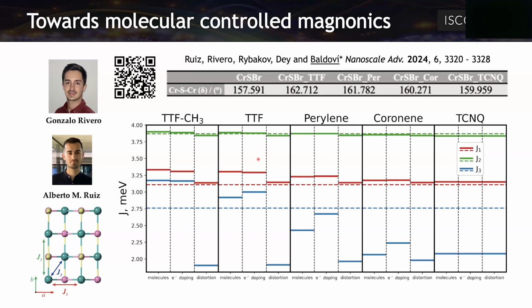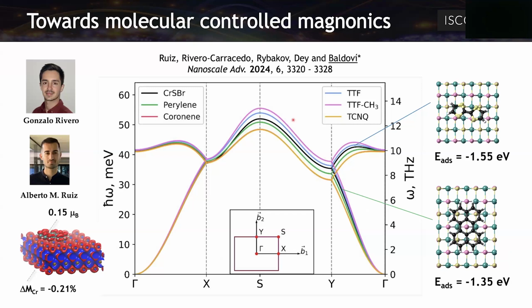This is one real advantage of having now this relation between the energy of the HOMO and the conduction band minimum. And here we have also the effect of the distortion that we observed, so the effect of charge transfer is increasing this from the distortion. Regarding the magnon dispersion, we observed, especially here in gamma Y, because we are affecting mostly J3, as I said before, that the TTF-CH3 is increasing the group velocity, and also the TTF. The black is the pristine, and the other ones, because of the effect of the distortion, are decreasing the group velocity. So it's a way of tuning the magnon frequencies by using molecules, by charge transfer, especially as the main mechanism.